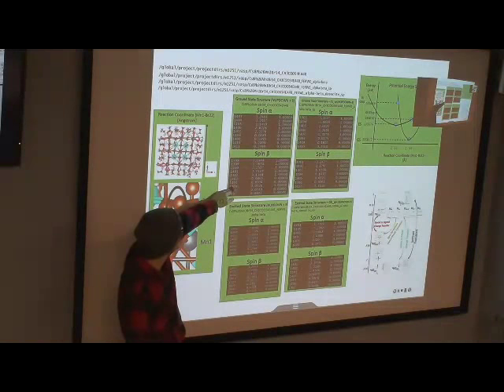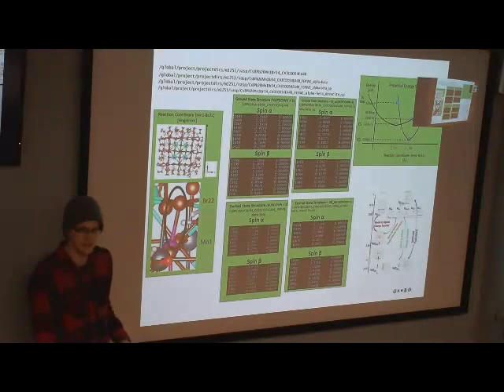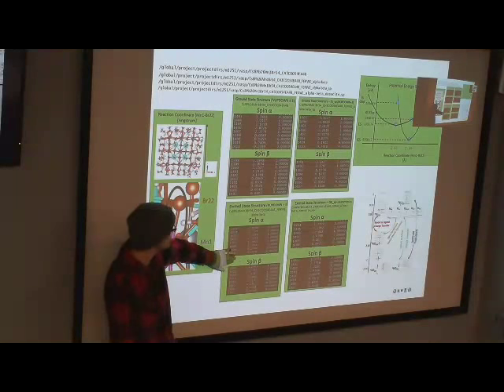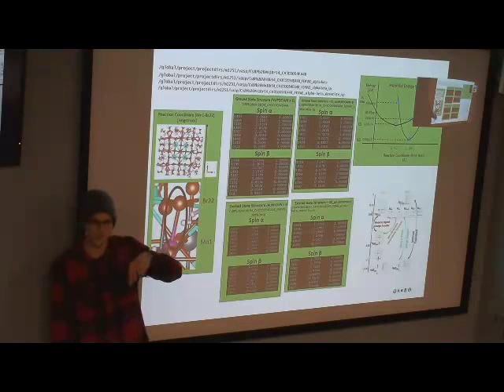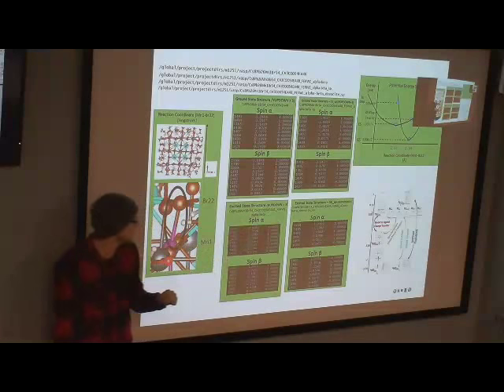To get a rough idea of what the reorganization energy in the system is, you need to make 2 parabolas for potential energy surfaces, and you need 4 points. Here is the ground state geometry optimization, spin polarized, in a high spin configuration, because from previous work we found that high spin is the lowest energy. So then we have a ground state structure. Then we also do an excited state geometry optimization for the optical transition that occurs in the system, which is a spin flip from alpha to beta. So it's basically a geometry optimization with n up down equals 3. That forces it to take the spin configuration that it would take for an optical transition.